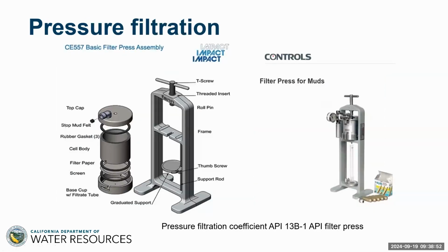Pressure filtration might be something that you're less familiar with, and this is still a test on the fluid grout. Basically, once we start pressurizing a fluid grout, this pressure filtration coefficient measures how well it retains the water, because the water is basically just a lubricant in the grout. And remember, grout is not a solution, it's a suspension of cement particles and water. Therefore, if a grout is formulated that can hold in the water, that means that the grout can travel further and more efficiently. And if we were thinking ahead to grouting very fine slots or perforations in casings, then an unstable grout in pressure filtration will just basically filter itself and smoosh over, that's a very technical term, the individual perforations, and therefore stop the grout escaping.